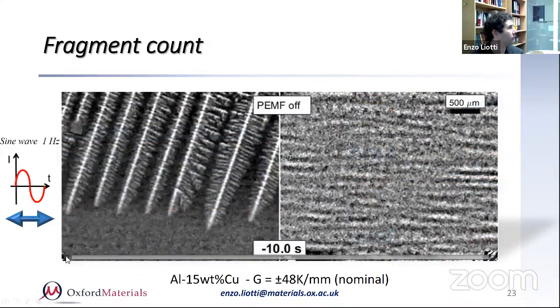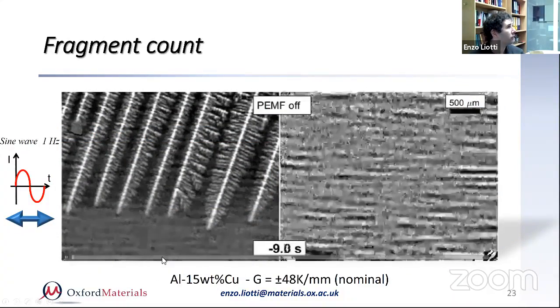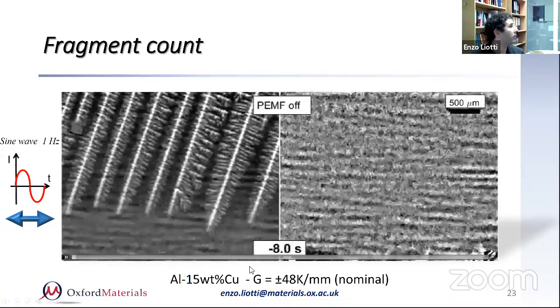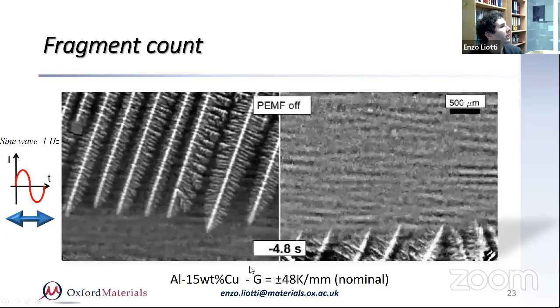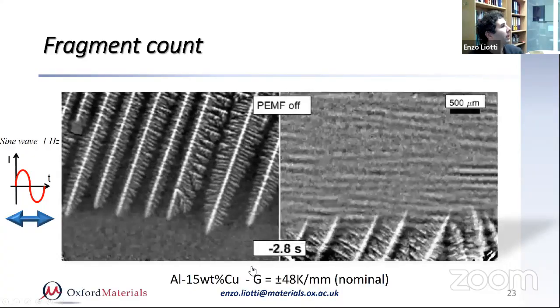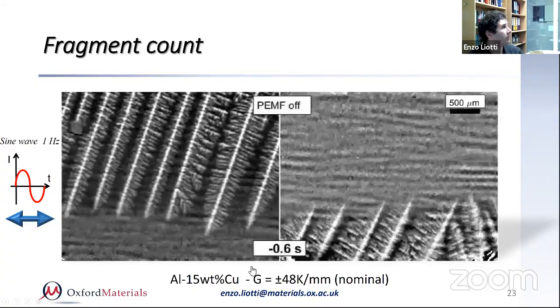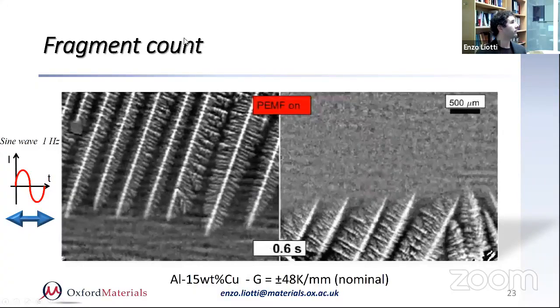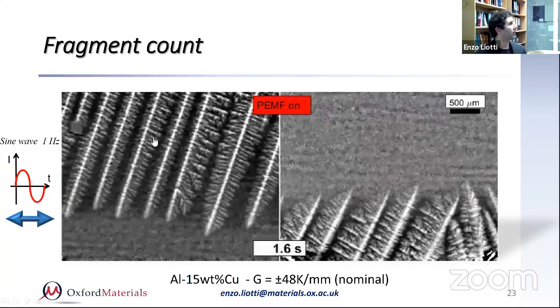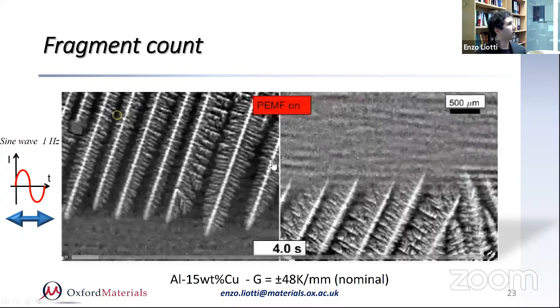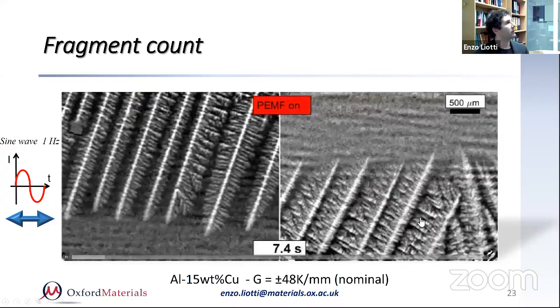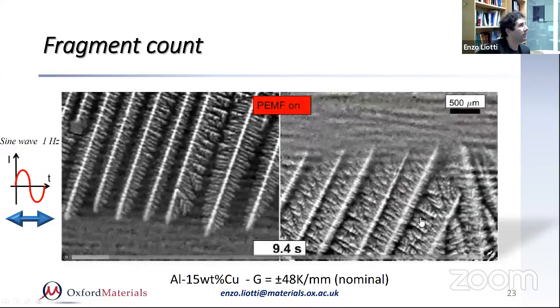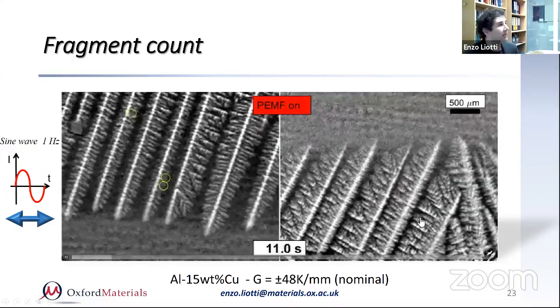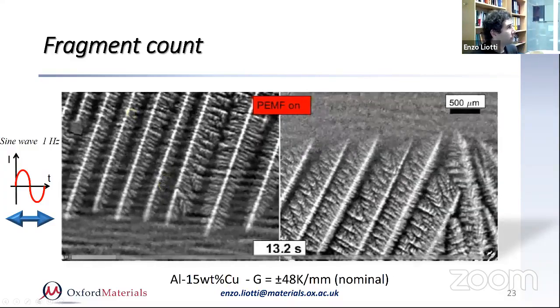So this is an example of the difference of the growth direction. So these are two arrays which are equivalent in everything apart from the direction. So when the PEMF starts, you can see that at some point, when you see the yellow, there is actually a breaking, right? And normally breaking doesn't take place immediately. It always takes a bit of time, about a few tenths of seconds.